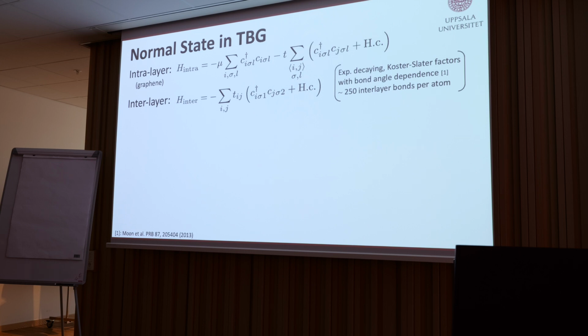The first fascination, at least to me, in this material is that you need a lot of interlayer bonds to accurately get the normal state. To capture the intralayer physics, you just need nearest neighbor. To accurately capture the Moiré spectrum at the magic angle, you need around 250 interlayer bonds per atom. So you have very long range hopping, you need to go across, and the distance between the layers is bigger than the distance in the plane. This at first seems very strange, but this is what you need to do to get the accurate band structure.